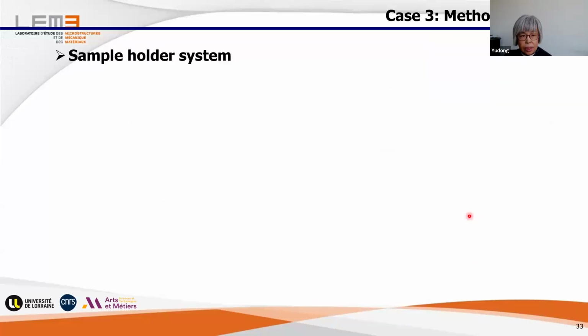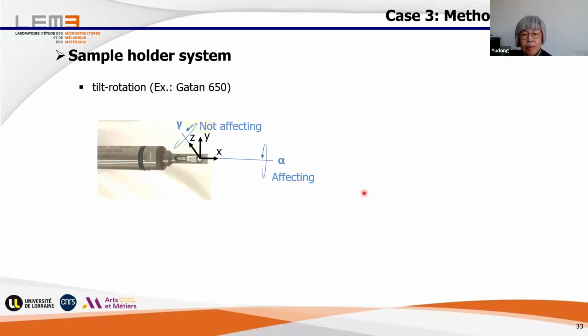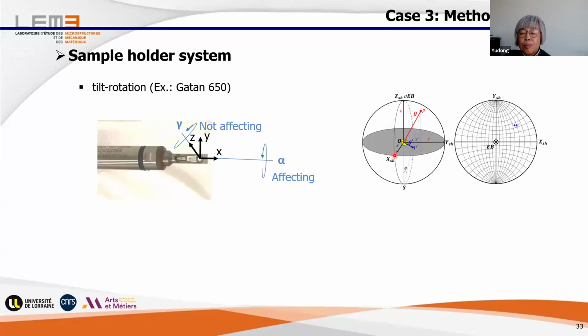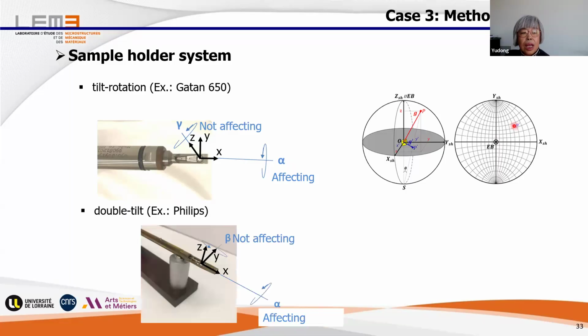Okay, and now I have to explain a little bit about sample holders, because we have different sample holders. One type of sample holder is where we can rotate the sample around the z-axis, and this axis is normal to the sample surface. We can also tilt the sample. This is called the gamma rotation, and we can tilt the sample around the x-axis, and this we call alpha tilt. For this, we use the pole figure projection on this equatorial plane, and this is in the software. The beam direction is here. And so we have a pole here of an individual crystalline direction.